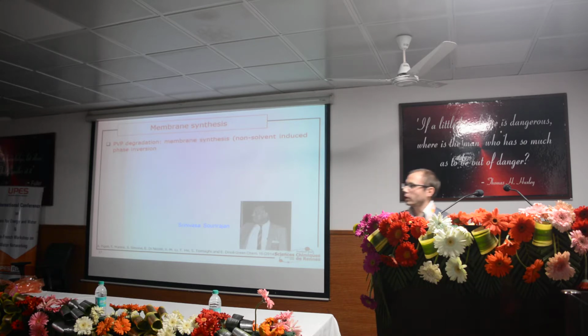Until now, I only talked about PES, but there is also some PVP in your membrane, and of course we also want to know if PVP is degraded. To do that, we have to synthesize our own membrane, because when you buy a membrane from a supplier, you know that it's a PES membrane. They don't tell you if there's PVP inside or not, and if they tell you, they don't tell you the amount of PVP. But from our side, we needed to know exactly which amount of PVP was inside the membrane.